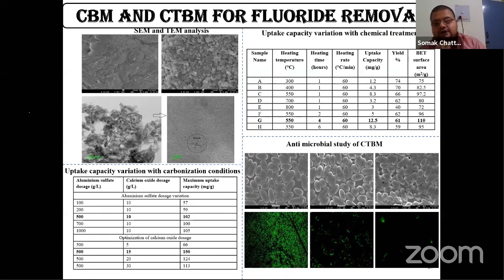So after all the experimentation was done, we were able to conclude that a heating temperature of 550 degrees Celsius, a heating time of 4 hours and a heating rate of 60 degrees Celsius per minute were able to achieve a fluoride uptake capacity of 12.5 milligram per gram with a yield percentage of 61% and a surface area of 110 meters squared per gram. Now, this was our final material from the partial carbonization process.